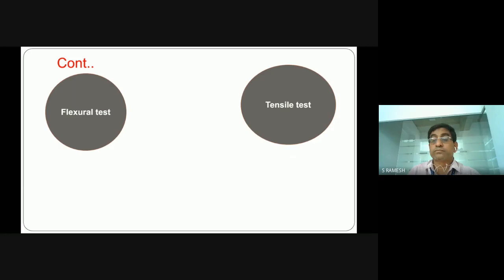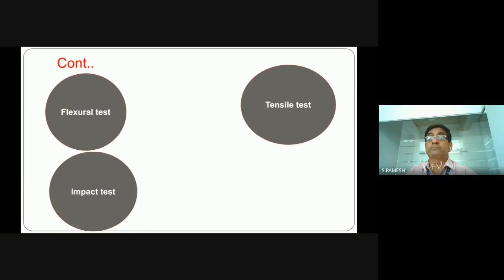And then tensile strength, we used the standard ASTM D638/10. We prepared a specimen dimension of 165 into 25 into 3 mm thickness, and we used a gauge length of 100 mm. We will go for a universal testing machine, with a crosshead speed of nearly 5 mm per minute.